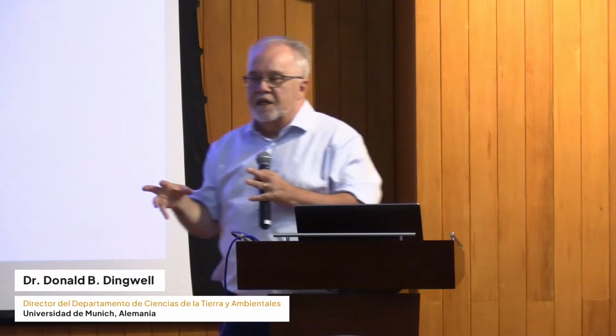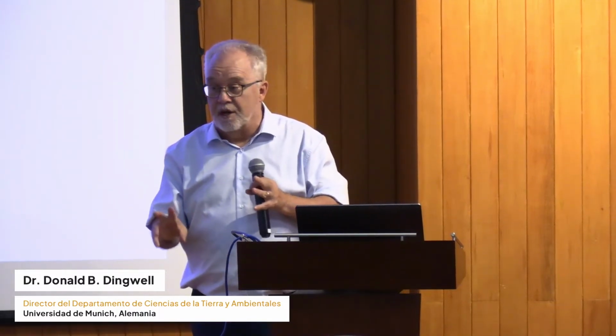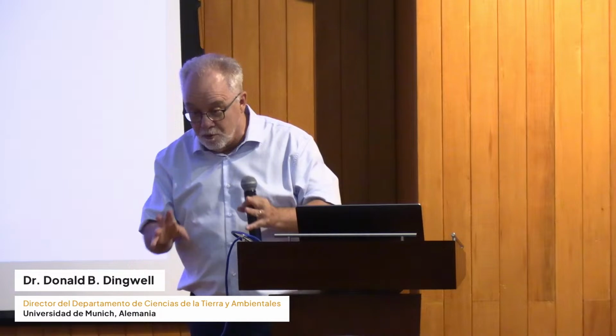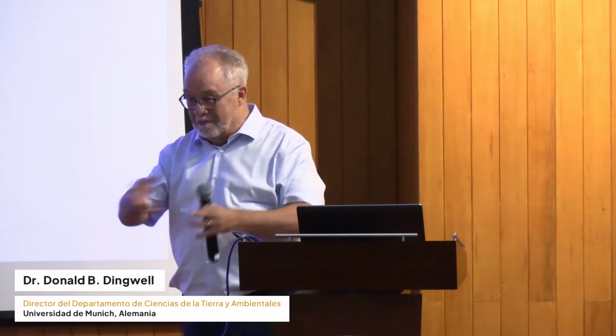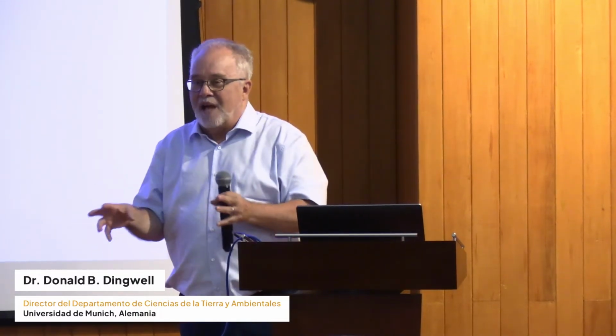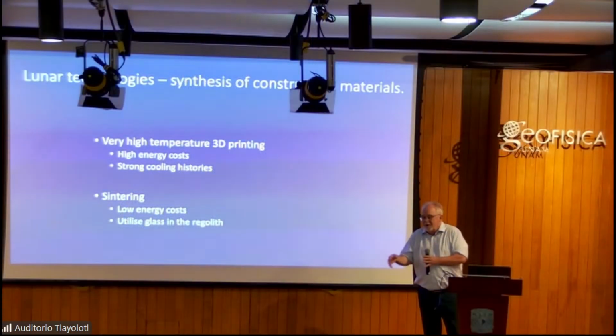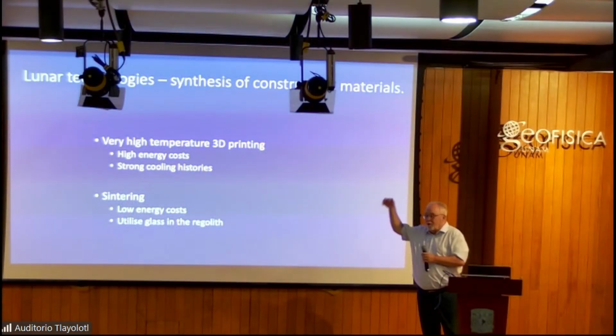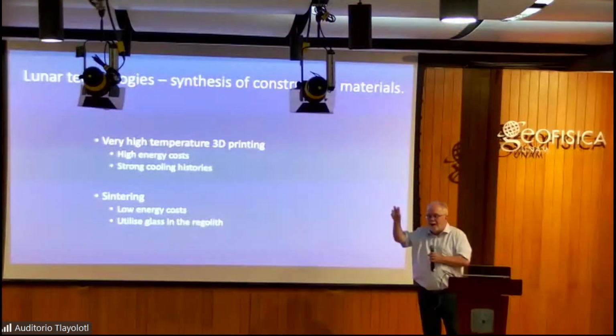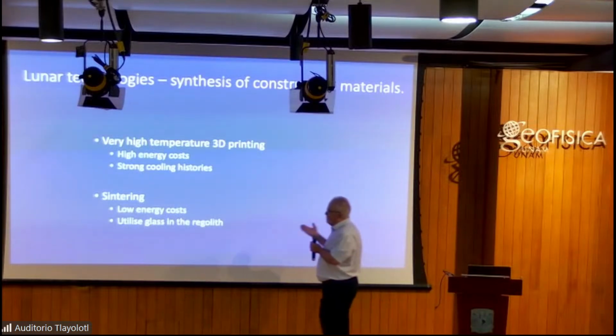And in a sintering experiment, the amount of strain that you're talking about, and therefore things that can go wrong because you're juggling stuff which is hot, is tiny, because the amount of strain in sintering is mesoscopic. You can't even see it from the outside. Yeah, the brick gets a little smaller. Whereas if you're pouring liquid from 1600 degrees C, everywhere there's strain in hot materials, something can go wrong. So you see already, I'm a big fan of sintering, although I love to melt rocks.